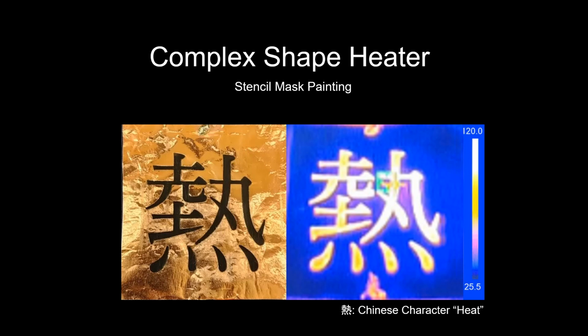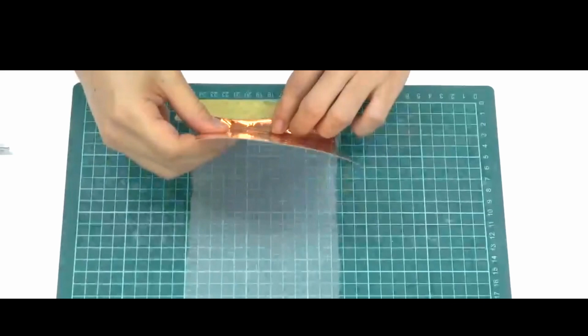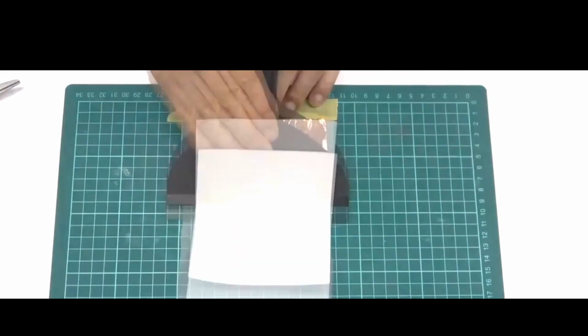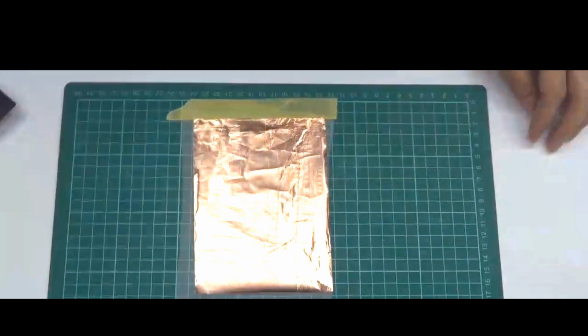Next, we would like to introduce the stencil mask painting technique to create complex shape heaters. We made a heater with the shape of the Chinese character for heat. We use copper tape film as the electrode and silk mesh as a substrate to absorb the heating paint. First, we attach the copper tape film to the silk mesh with a spatula.